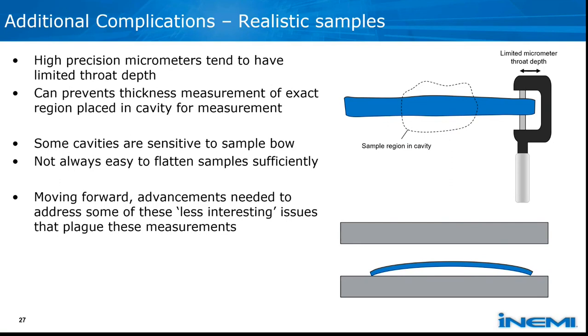We also found that some of the techniques are sensitive to bows in the material samples, and it's not always easy to make the realistic samples perfectly flat when you put them into the equipment sets. So moving forward, we probably need advancements to address these problems, which I've categorized as less interesting technically, but they're very practical and lead to significant errors in the assessments. They generally affect all the measurement techniques because all of them rely on understanding the material thickness and, in most cases, assume some flatness.